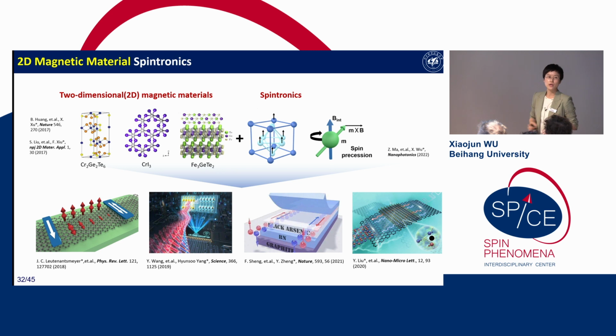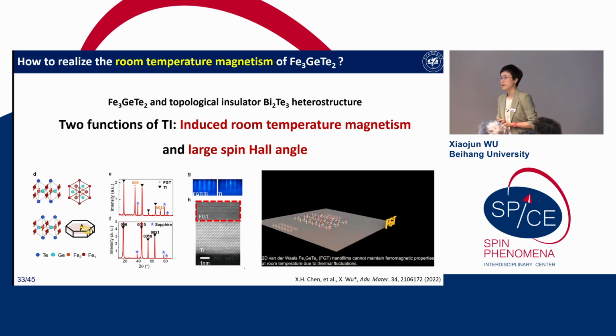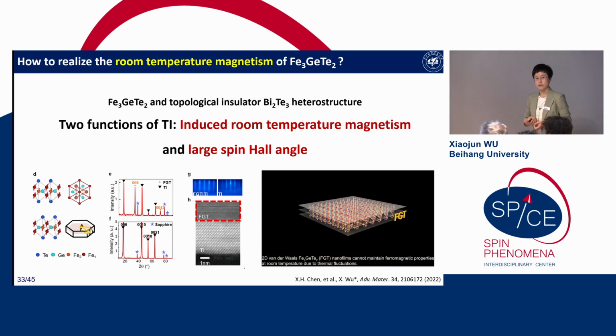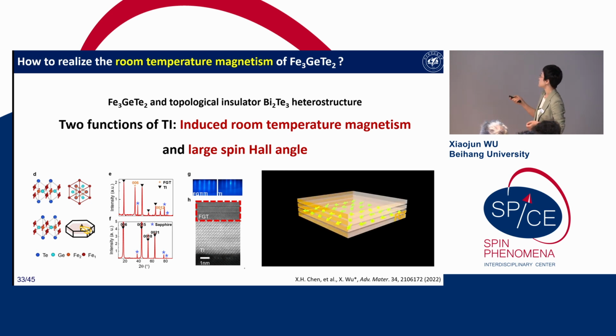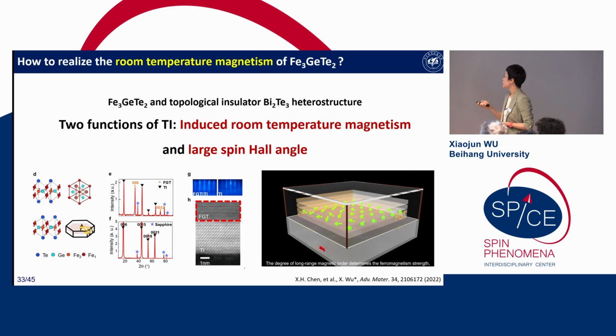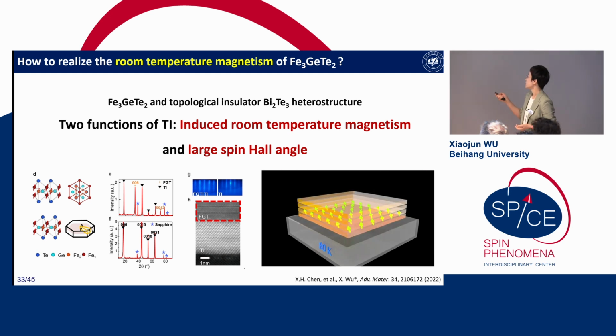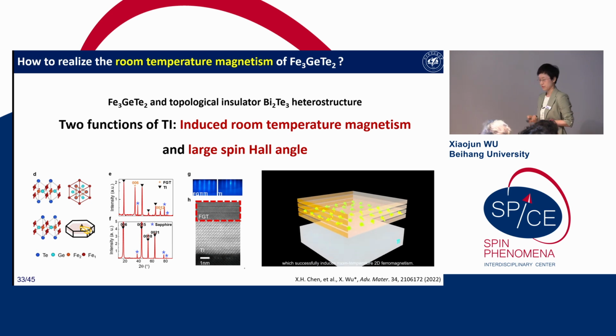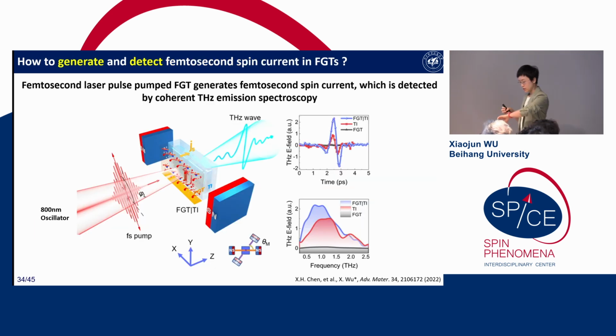So people are trying their best to produce 2D materials that can work at room temperature. One possible way is that we directly attach a topological insulator onto the 2D material. Here we could choose iron germanium telluride, and the topological insulator bismuth telluride. They have two functions. The first one is that it can induce the room temperature magnetism. The second one is that it offers a very, very large spin Hall angle. So it means if we use this kind of heterostructure and illuminate it, we can also have the chance of getting terahertz.